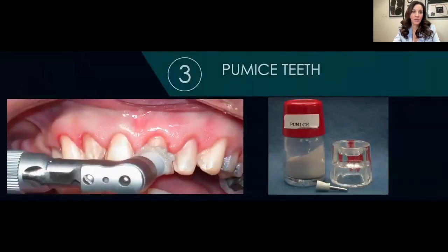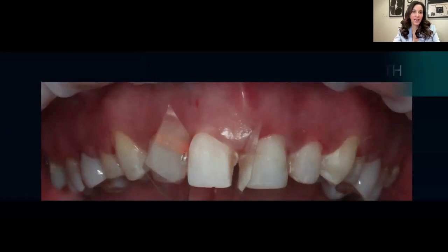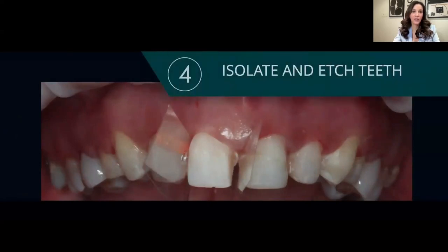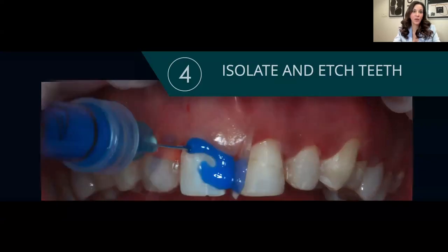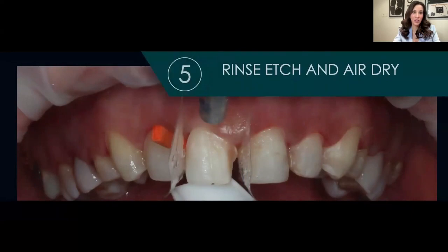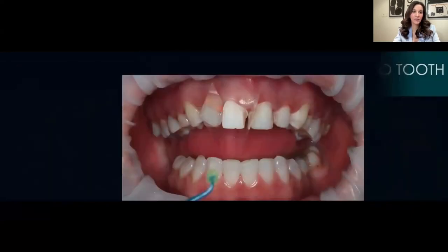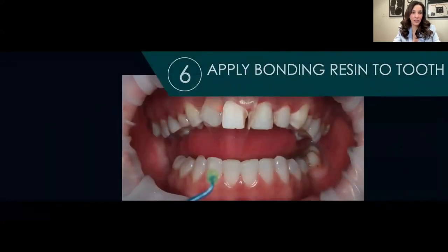You want to, of course, pumice and clean off your teeth, isolate your teeth with either rubber dam, or in this case, mylar strips, a wedge, and an Optigate. You then want to etch your tooth. You want to rinse off the etch and air dry it. You want to apply your bonding resin to the tooth, and depending on the manufacturer, either cure the bonding resin or not, depending on your manufacturer.